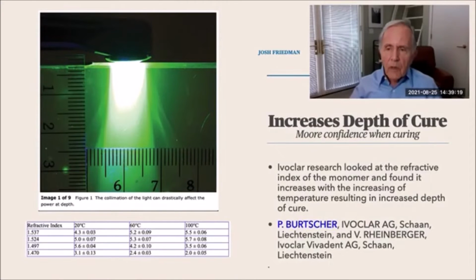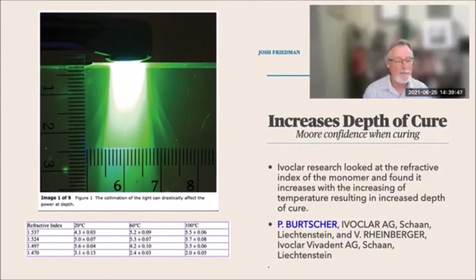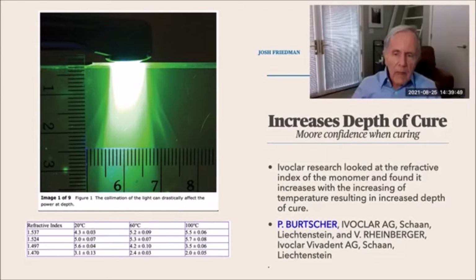The depth of cure was done by the researchers at Ivoclar, and they looked at something called refractive index. They found that the refractive index of the composite material increases as the material is heated, and that's what this data is showing here. And that, in effect, also causes the increased depth of cure. So if the light can get down into the material because the refractive index is higher, that's just another way of confirming that we're getting greater depth of cure.